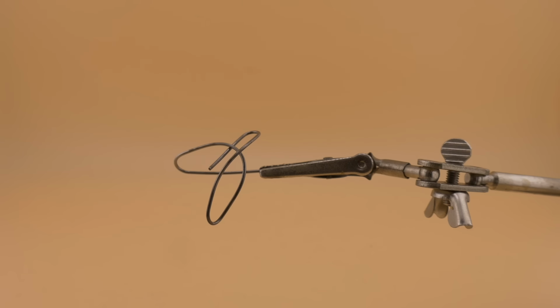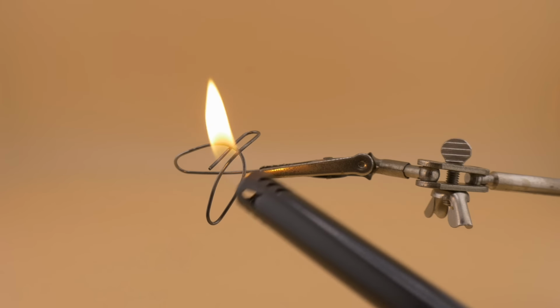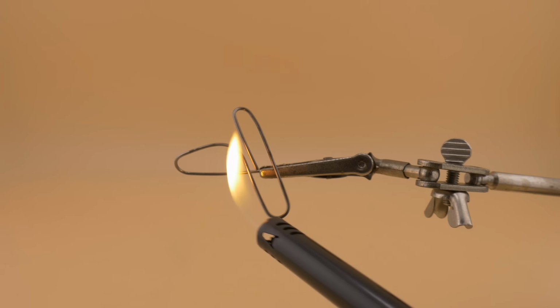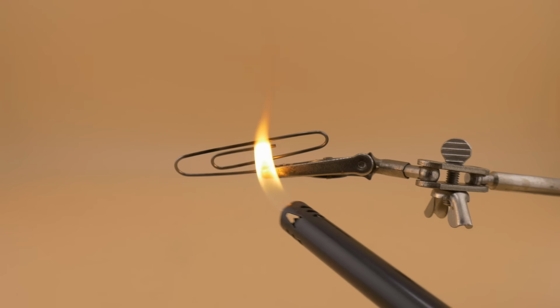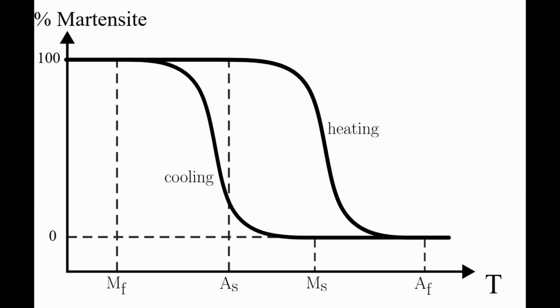And this is what we show here. I have this paperclip made of nitinol. As you can see, I shaped it differently, and now that I heat it, it will just spring back to its paperclip state. These properties come from a solid-state phase transformation between two different crystal structures: a low-temperature phase called martensite and a high-temperature phase called austenite. Similar terms are used in steel, but a different mechanism.